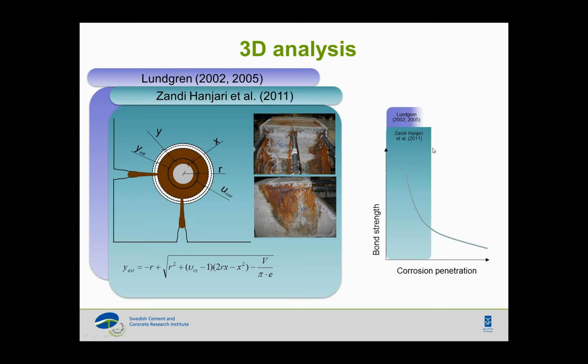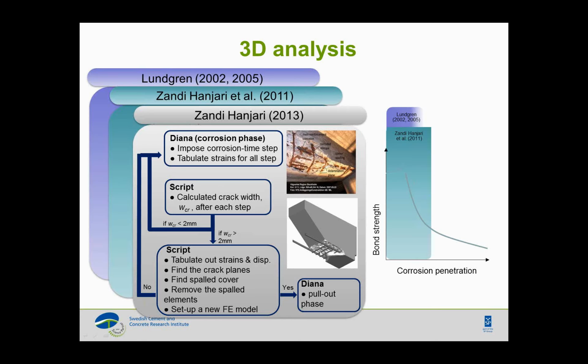We go back to the analysis environment in Diana, but in this case we deactivate all the elements which belong to the spalling part. As you see in this figure, all these elements down on the bottom, they all correspond to the delamination plane. And then we go back to the Diana environment, deactivate all these elements and continue.